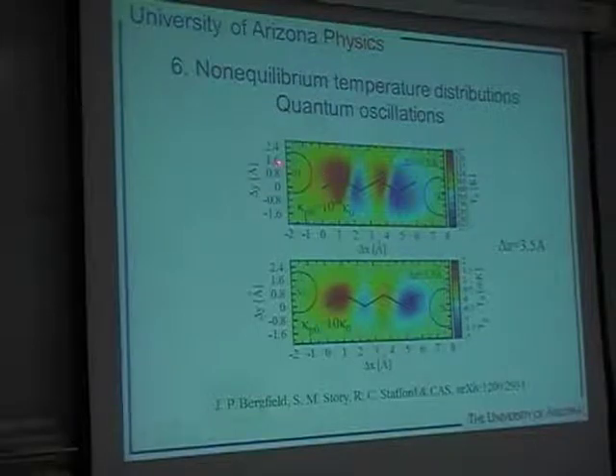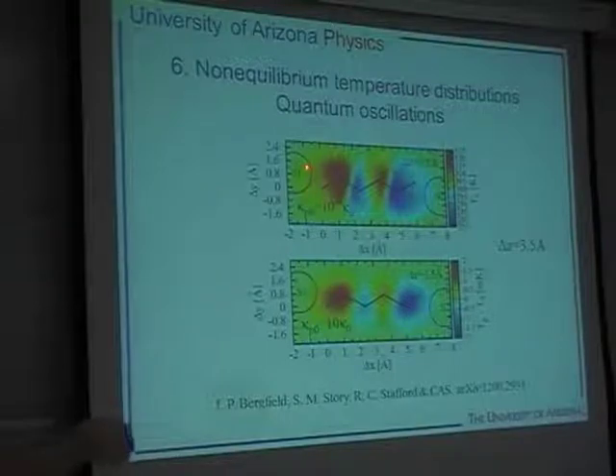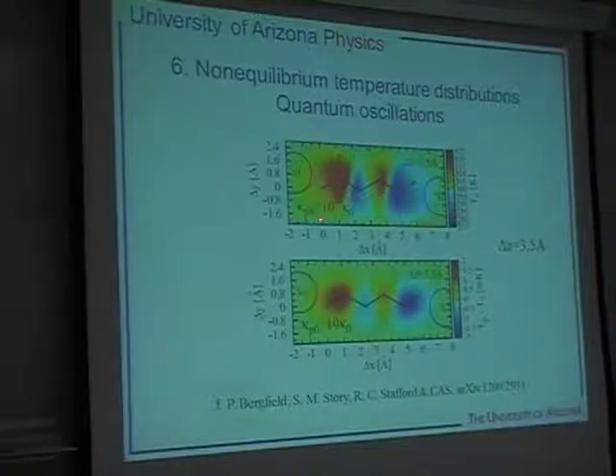And what you see is, there is kind of like a hot end of the molecule and a cold end of the molecule, but the temperature drop is not monotonic. You get this oscillation, hot, cold, hot, cold. Now this particular one is taken with a thermal coupling between the probe and the environment of about 10 to the minus 4 conductance quanta, which corresponds roughly to the case where the only coupling to the environment of the probe is through blackbody radiation.